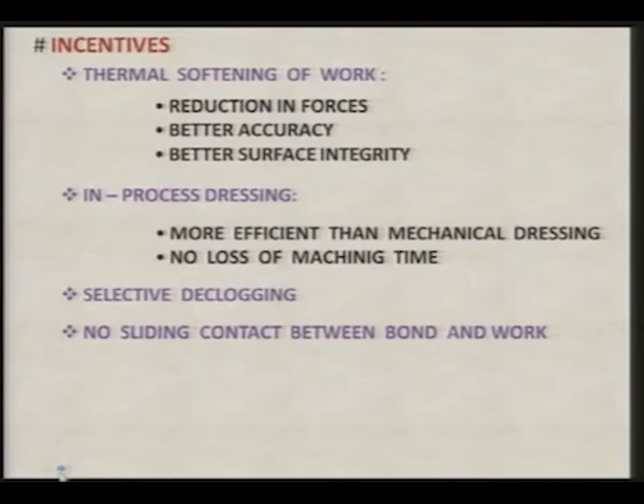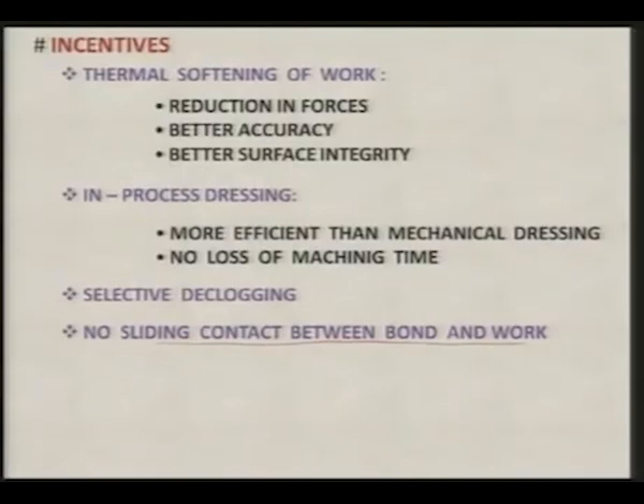Now, since continuous dressing and declogging of the grinding wheel are taking place, abrasive particles and only abrasive particles are always in contact with the workpiece. As a result, no sliding contact takes place between the bond material and the workpiece material. Here one point is very important to note. The bonding material should be metallic, it should be electrically conducting, otherwise it will not work in electric discharge abrasive grinding or electric discharge diamond grinding, because we have already seen that in EDM the cutting tool acts as the cathode and the workpiece acts as the anode. In electric discharge diamond grinding also the grinding wheel is acting as the cathode and the workpiece is acting as the anode. If the wheel is to act as the cathode, then definitely it should be electrically conducting material.